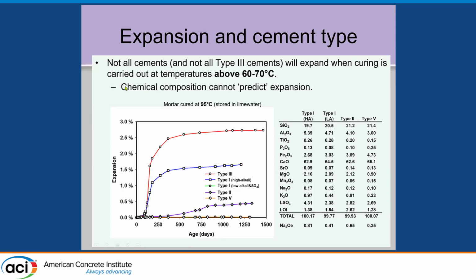But various people were doing research on this at the time and looking at chemical parameters, but chemical composition cannot predict whether they're going to expand or not. Somebody came up with a formula, you apply other data to it and found it didn't fit anymore. So here's some examples. There's a type 3 that expanded. There's a type 1 high alkali that's expanded. Meanwhile, a type 2 expanded, but not a type 5 or a type 1 low alkali cement. So there are certainly cements that are more susceptible than others.